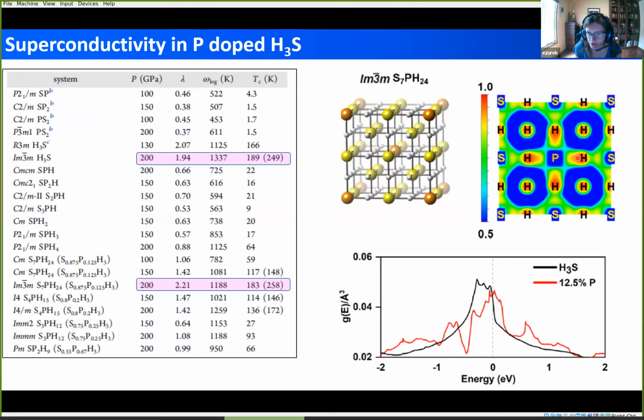Here I show the electron localization function, which indicates that this system has more of a phosphorus hydrogen sulfur type bond. Indeed, if you look at indicators such as the crystal orbital Hamilton populations, we see that doping with phosphorus doesn't change the strength of the sulfur hydrogen bond as much as doping with carbon did. That has to do with the ionic sizes, the electronegativities, and also the fact that phosphorus likes to be octahedrally coordinated.